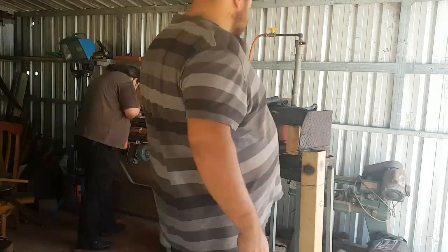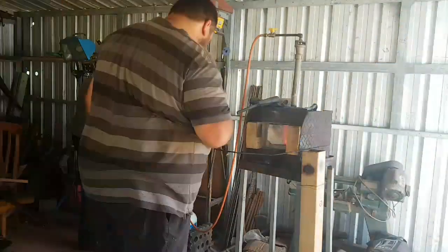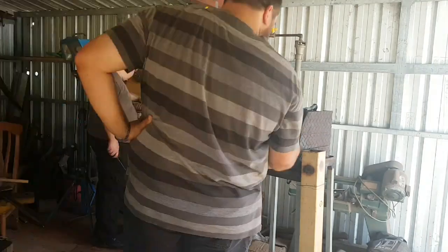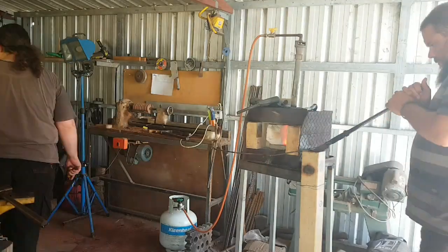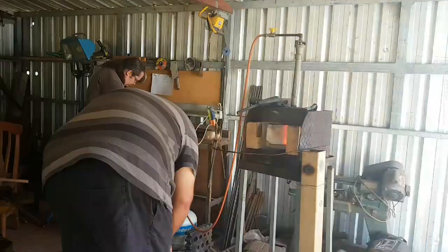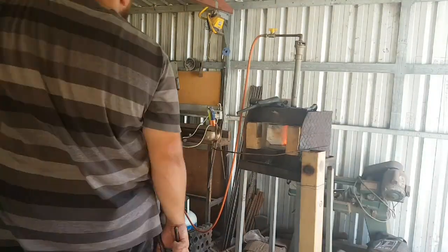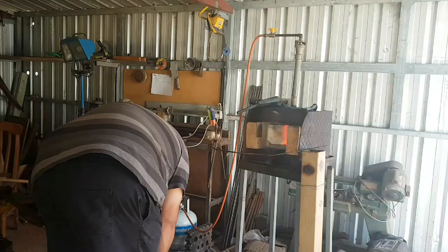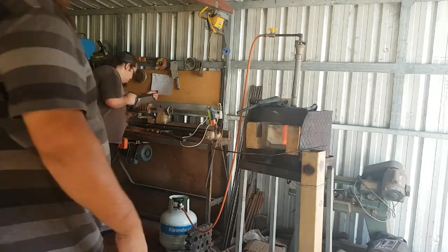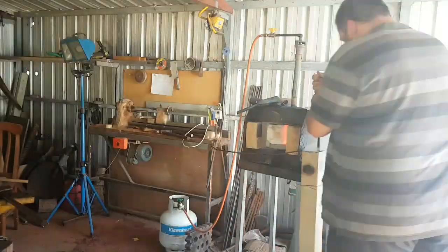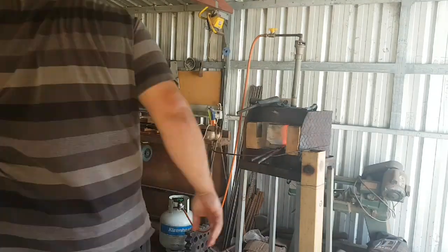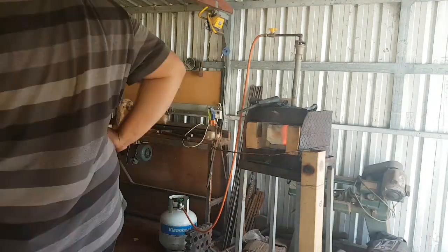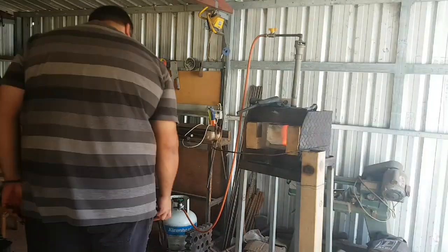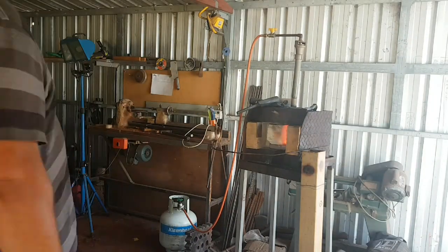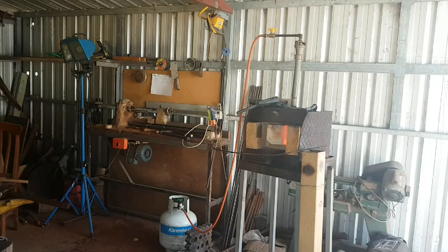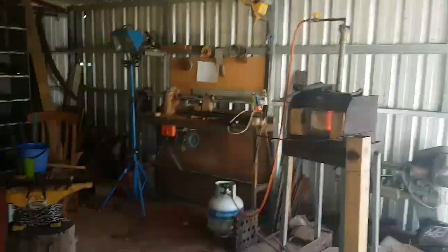And so all of them went into the tempering oven at about 175 degrees Celsius for 2 cycles of 2 hours. And in previous testing, I know for a fact that the 1084 and 5160 Damascus will come out to about 58 to 59 Rockwell. These are all Rockwell tested by my fellow knife maker, the one I'm collaborating with. The other blades will probably sit around the same, being that they are of a similar kind of alloy.